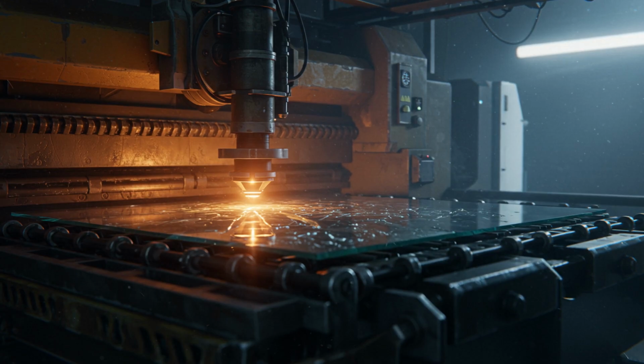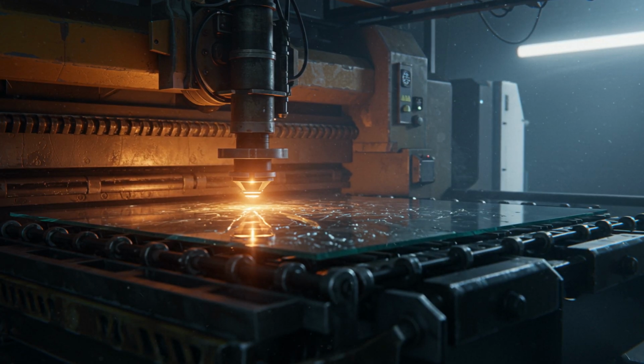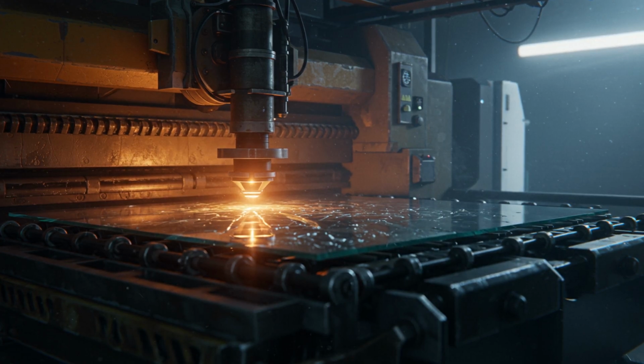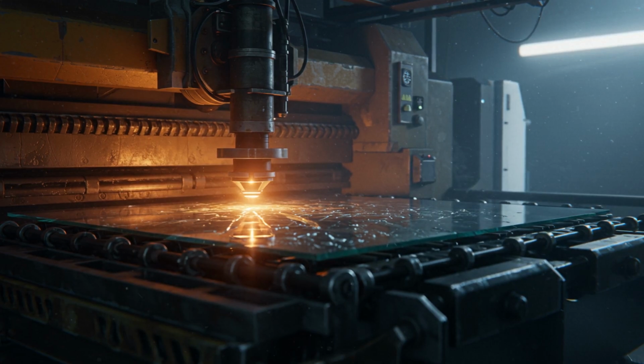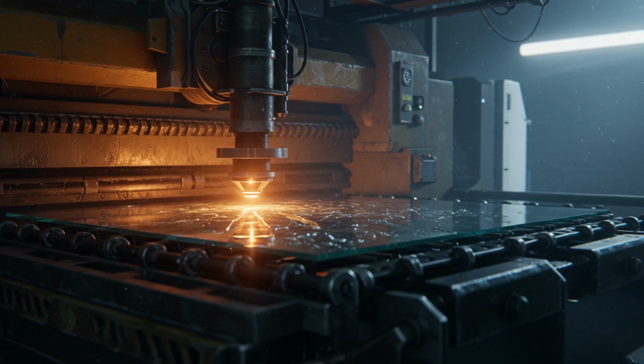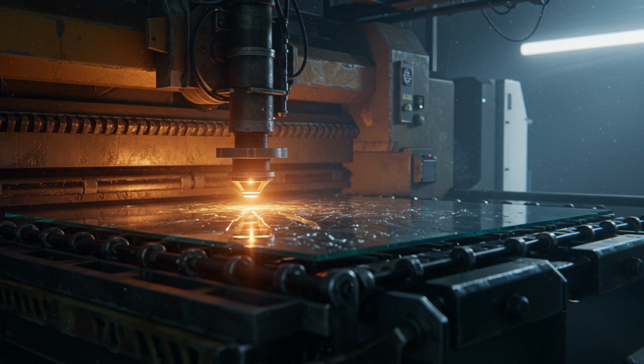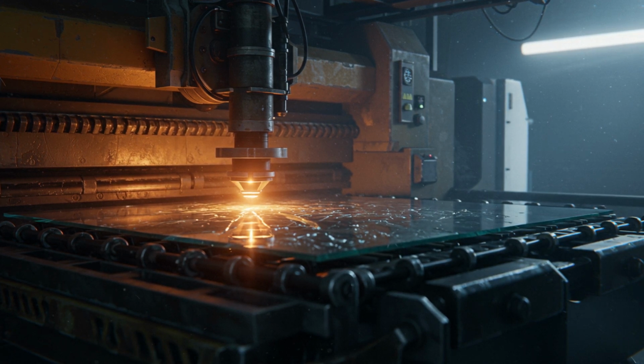Diamond-tipped wheels or high-power lasers create a microscopic fracture line on the surface. Precisely timed mechanical snappers then apply pressure, causing the glass to break cleanly along the scored line. The edges are often jagged and sharp, so they pass through a series of grinding wheels that smooth the perimeter to a pencil edge or bevel. For specialty glass, like that used in high-performance electronics, the precision is measured in microns. This is the final stage for clear glass, but for the world of mirrors, a secret chemical process is about to begin.